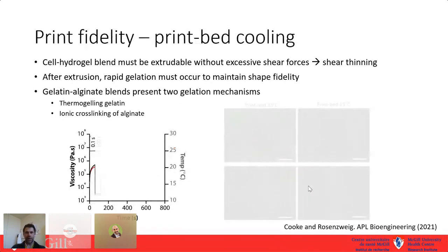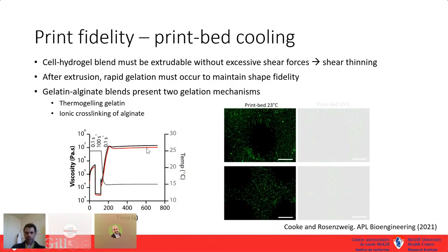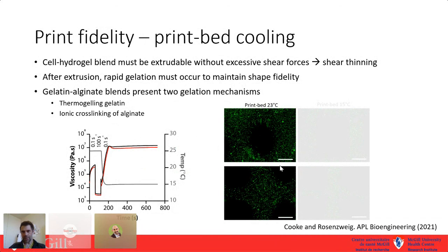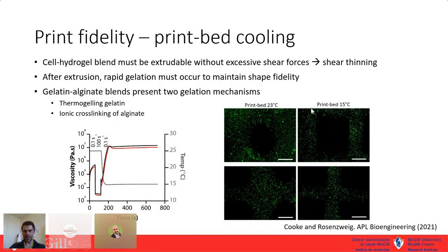Megan has tested all the rheological properties of these hydrogels for their ability to be printed in an extrusion bioprinter. She demonstrated quick recovery after printing. Understanding these parameters is critical because if the print bed is too warm, you get oozing and lose the open pore network needed to supply nutrients to all cells. By carefully testing different cooling bed temperatures, she showed that print fidelity is well-maintained. This demonstrates the importance of print parameters for this gelatin-alginate hydrogel.